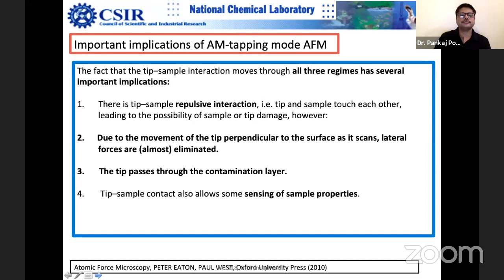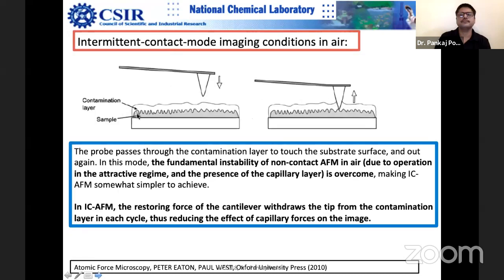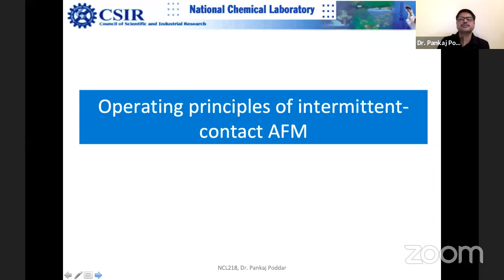Okay, so let's move to the next slide. You can see that there is always a contamination layer, which is normally water. And the tapping mode advantage is that the spring constant is so high, and it has so much energy, that it can break free of these capillary forces, touch the surface, and then pull back in both movements. This is the advantage, that capillary forces can be overcome when you are measuring, which is not possible for non-contact measurement.